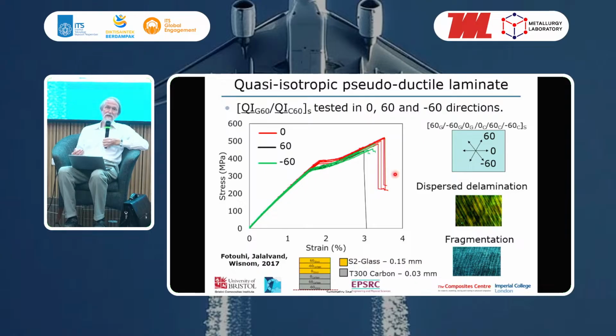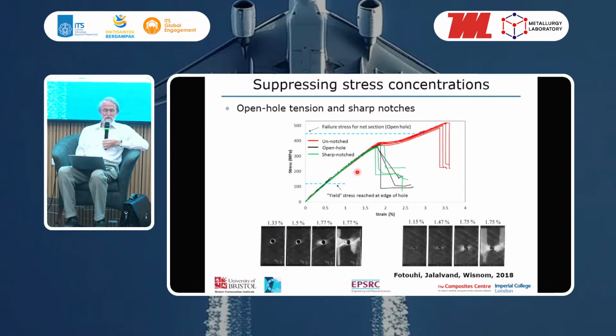So the whole point of doing this is to try to achieve a more gradual failure. And the way we investigated this was to look at what happens when we put in a stress concentration. As I was talking about in my lecture on Thursday, composites are very susceptible to stress concentrations. If you put a hole or sharp notch in a composite, you typically see a big reduction in static strength. So by putting this pseudoductile mechanism in place, the idea was to try to reduce that notch sensitivity. And this shows the results of that same layup I've just shown, but this time with either a hole or a sharp crack in the layup.